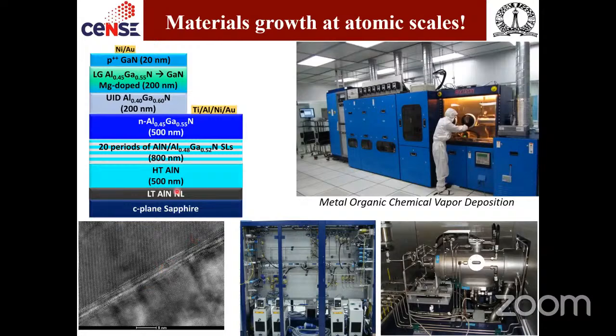For instance, this is the aluminum nitride and sapphire interface. If you look at it in an electron microscope, you can resolve atomic columns. All these dots that you see are actually atomic columns. You can look at the length scale here, which is 5 nanometers. The inter-dot distance is about 5 angstroms, which is 0.5 nanometer, and that's about the bond length of these materials. You can nicely resolve all these atomic columns in this powerful electron microscope.